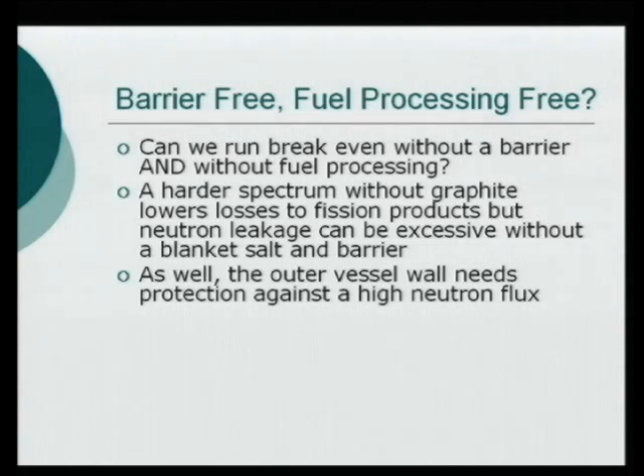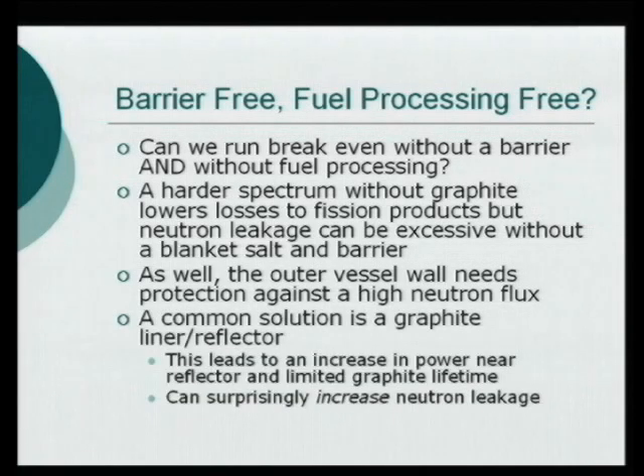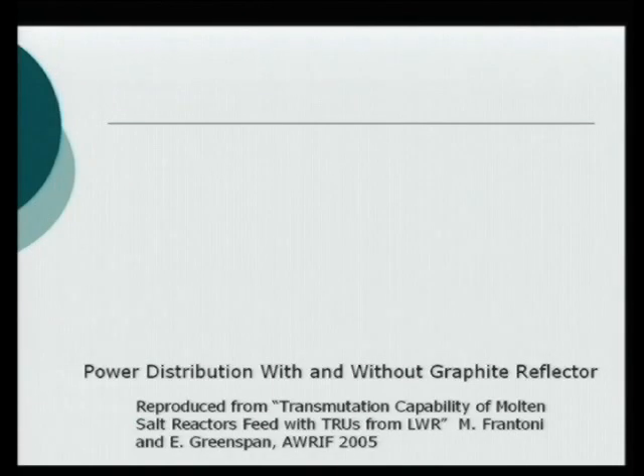Now, the other thing we have to keep in mind is that outer vessel has to be protected against a high neutron flux. And a common solution, if we're talking about a tank of salt idea here, is putting a graphite reflector. Okay, that sort of protects things. But it's a very surprising result that it can actually start to increase the neutron leakage, because what happens is you get sort of a much bigger increase in power at the outer edge. And I'll just show you a quick